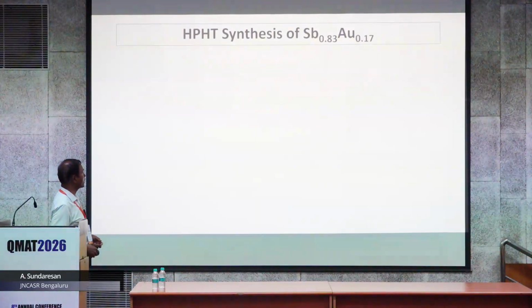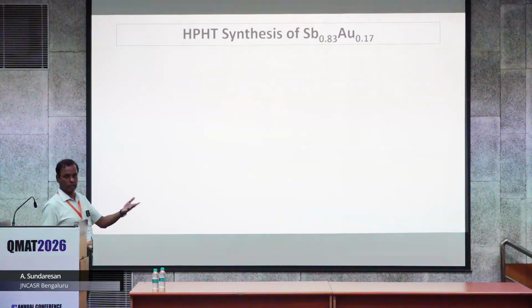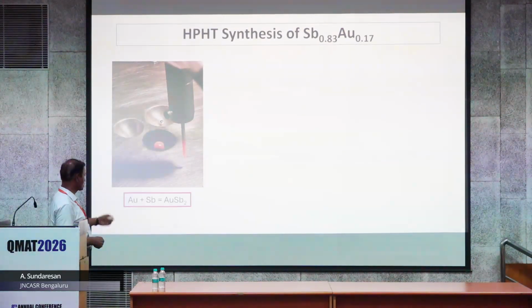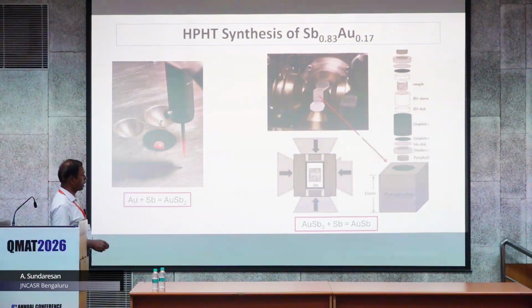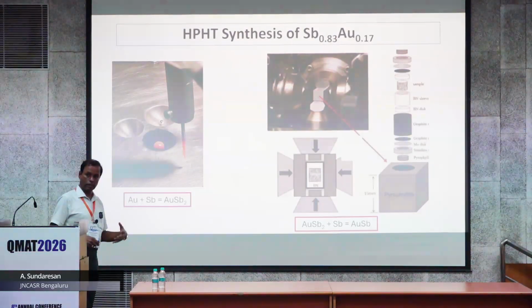We prepared this material, selecting one composition expected to give the highest Tc in this alloy system. We did this through a 2-step process: first arc melting with a suitable composition of Au and Sb, then adding extra Sb to bring the composition close to Sb 0.83 and Au 0.17. This is the cell configuration - a cubic anvil type setup, where you can apply pressure and temperature, and then quench it after heating.